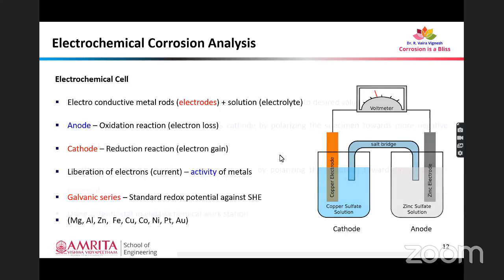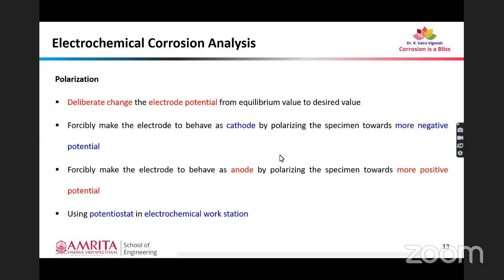So what we do in a polarization test is we deliberately change the electrode potential of the specimen from the equilibrium value to the desired value. That is done with respect to more negative and more positive corrosion potential. For example, in the first instance, we forcibly make the electrode behave as a cathode by polarizing the specimen towards more negative potential. After that, we bring back the potential of the specimen towards its original form. Then we forcibly make the electrode behave as an anode by polarizing the specimen towards more positive potential. And this is done using a potentiostat in an electrochemical workstation.